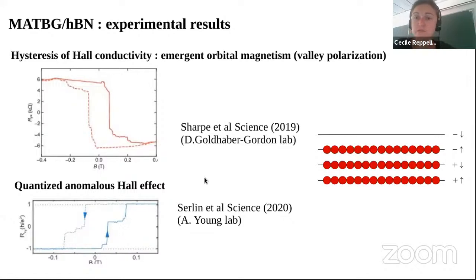And maybe I should explain that the hysteresis comes from the fact that as you increase magnetic field, if you have a very large magnetic field in one direction, you're going to fully polarize your system because the magnetic field couples to the Berry curvature basically in your system. And that's going to valley polarize the system entirely. And as you decrease the magnetic field going that way, you stay on the plateau of Hall conductivity because you remain in that polarized state, and you're still quantized at zero field. So you do indeed have a quantized anomalous Hall effect. There's no more magnetic field. It's a spontaneous polarization, spontaneous time reversal symmetry breaking. And as you go down to very negative field, you invert the polarization, like in a magnet.